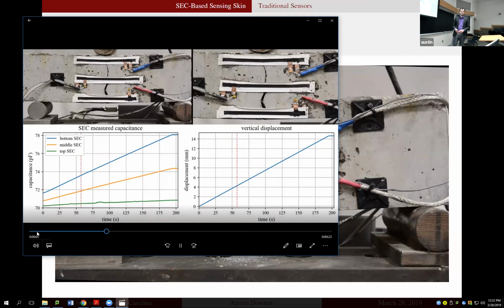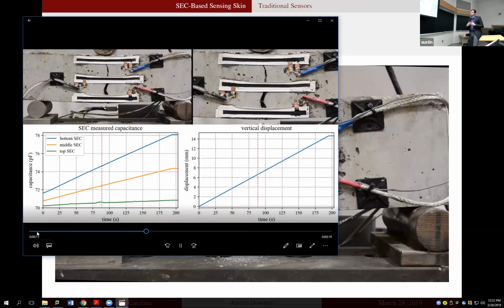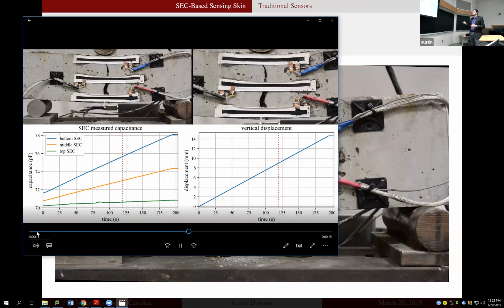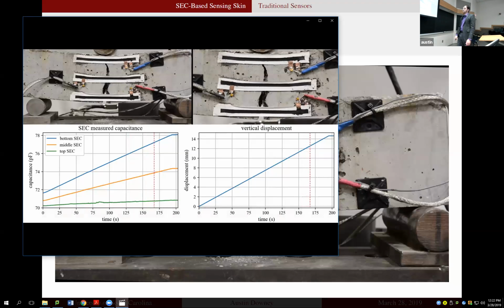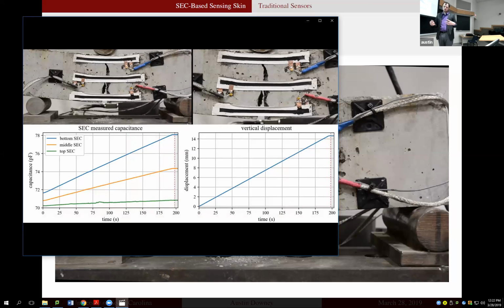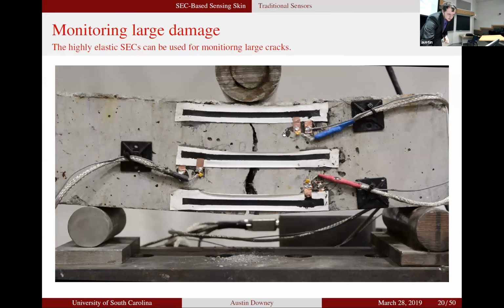Just continue. Okay. So if you can see the video, what you'll see is we have these 3 SECs mounted on the beam itself. And as the beam opens, we can track the opening using each one of the SECs. So these are highly elastic, and this gives us a flexibility that other sensors don't, right? Because we can use this over large openings and cracks, around corners, around welds. And the flexibility allows us to install them anywhere.